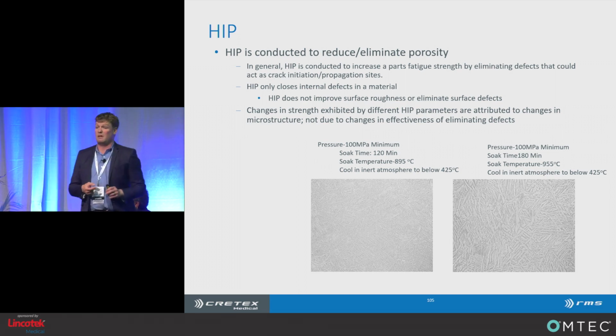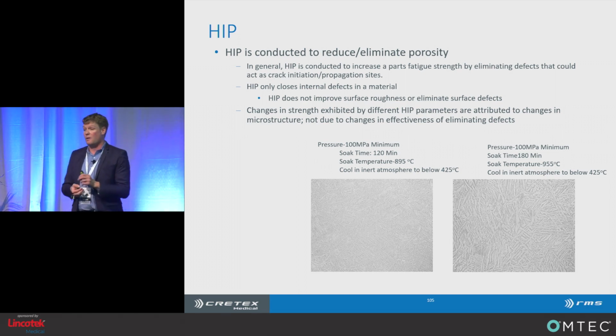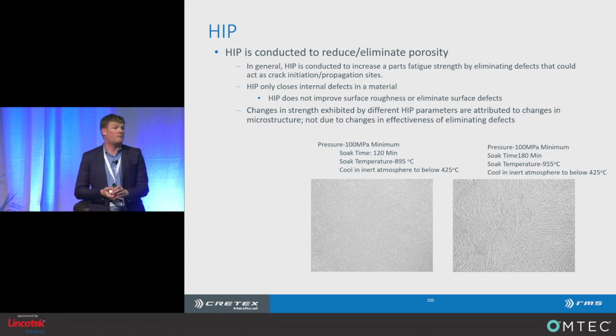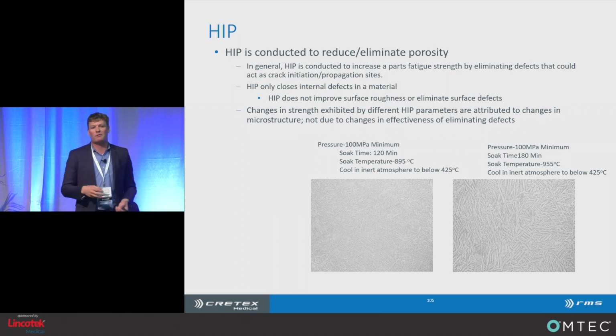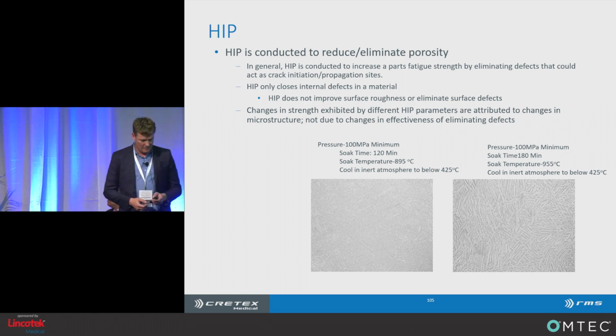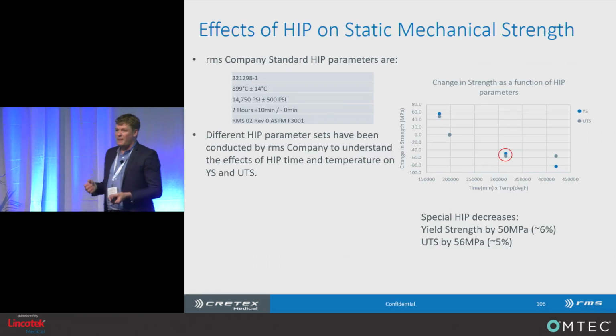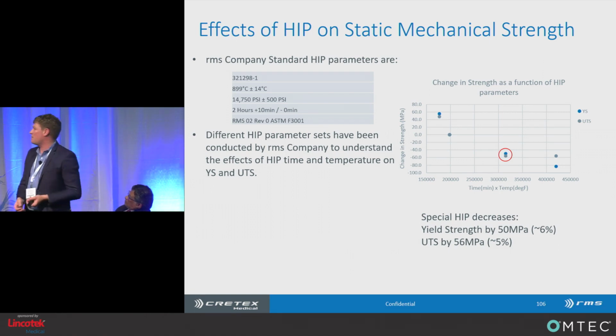Hipping won't improve your surface finish or remove any sort of defects that are on the surface of your part, but if there are small microvoids in your part, it can help push those out. Vacuum stress relief, on the other hand, will help with residual stresses and microstructure refinement, but it won't help you with those defects. So what happens when we change those hipping parameters?